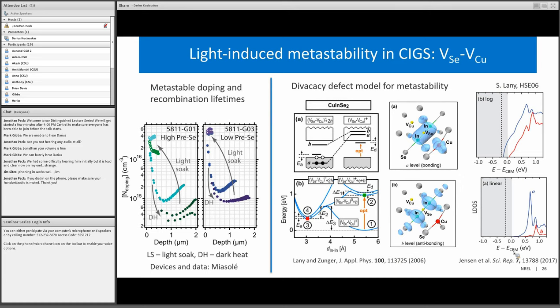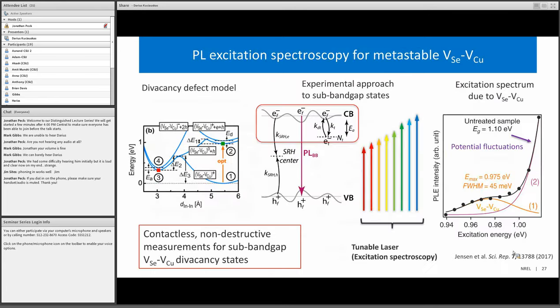More recently, Stefan Lany has repeated these calculations using modern first principles methods and found that the depth of that sub band gap state should be about 200 millielectron volts. And this is what we found in experiments in the lab, in that when we tune the excitation energy below the band gap, we can record the excitation spectrum, or just the absorption spectrum, of this metastable divacancy state, which is, as predicted, about 200 millielectron volts below the conduction band.